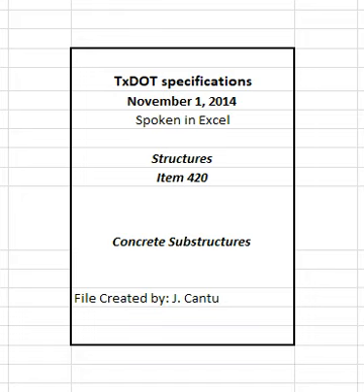Use strip chart temperature recording devices, recording maturity meters in accordance with TEX 426A, or other approved devices that are accurate to within plus or minus 2 degrees F within the range of 32 degrees Fahrenheit to 212 degrees Fahrenheit for mass concrete operations, cold weather placements, and as otherwise specified. 3.4 Artificial heating equipment.